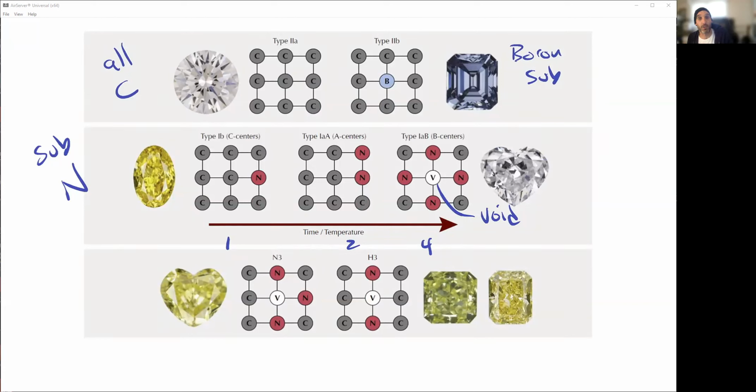So very neat stuff when you're looking at this. From a material science point of view, this is very cool. You can say, all right, I'm going to just substitute in some nitrogen and see what it's going to do. Or I'm going to try to knock out some of these and see what it's going to do. So very interesting stuff. In fact, the original synthetic diamonds that they tried to sell, by the way, just quickly, synthetic diamonds are exactly the same as regular diamonds. They used to use a special seeding method that would make them all yellow because they added nitrogen in. That's what they had to do to seed the crystals. And so you get these special colors. So it's very neat that you can tweak these things through just some amount of chemistry.